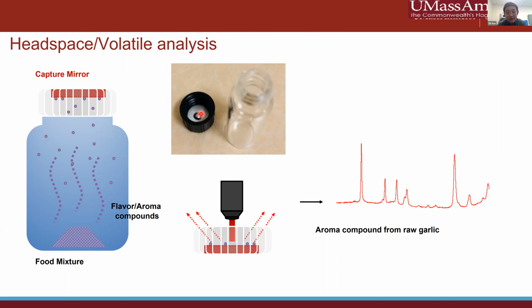We drop this mirror in this cap. This cap will then be capped on this vial and incubated with a garlic sample. So the volatile content of the garlic will be gradually released in the air and then eventually captured by this mirror. And then we just directly measure the mirror to give us any useful information. In this case, it's the disulfide compound from garlic. As you can see, we successfully recovered its signals.